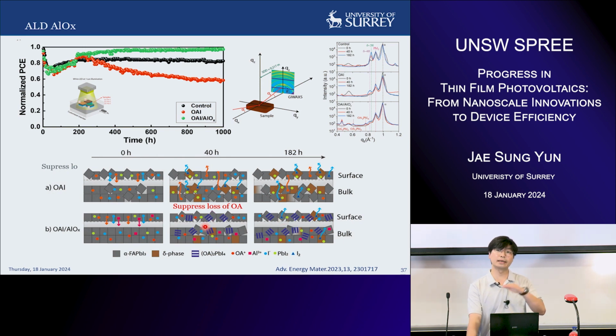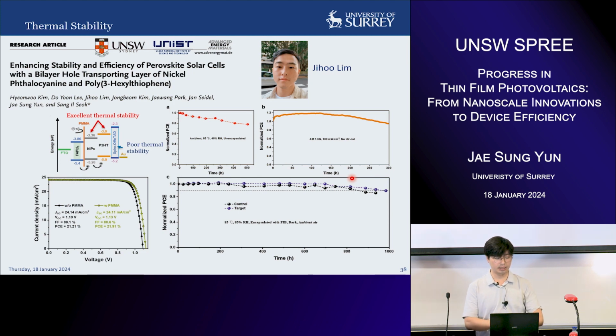So this 2D layer is hydrophobic and will definitely enlarge the stability, because it will suppress the volatile species from evaporating. We also did some stability studies with UNIST, and they employed a P3HT and nickel phthalocyanine layer. This sort of P-type layer has a very high thermal stability compared to conventional spiro material.